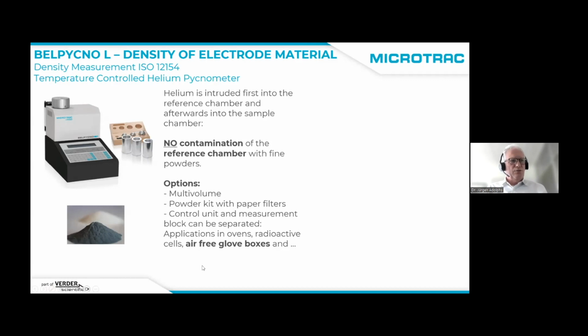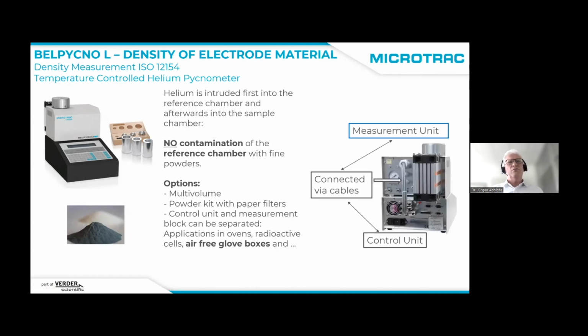But what we also do, since it's quite small, we can place it into an air-free glove box. In some applications, you should not have air or not even nitrogen. Under, for example, an argon atmosphere, you can simply put this instrument into a glove box. You can easily handle it with manipulators and work. It's also possible to separate the upper and lower part. It's temperature controlled via a Peltier temperature unit here. The lower part is the control unit. The upper part is the unit with the sample cell. And as said, it's also possible to separate this.